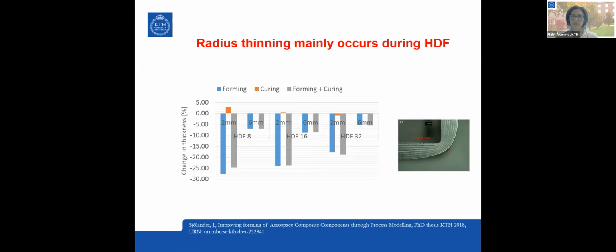Since we were mainly looking at the hot drape forming process, we started looking at what happened there. And we found that when you form different thicknesses of material, so hot drape forming 8 plies, 16 plies, or 32 plies, at different radiuses, using hot drape forming, we have the 2 millimeter radius and 6 millimeter radius. We could see that we had a certain change in thickness, which was quite large during the forming if you compare to the uncured thickness.